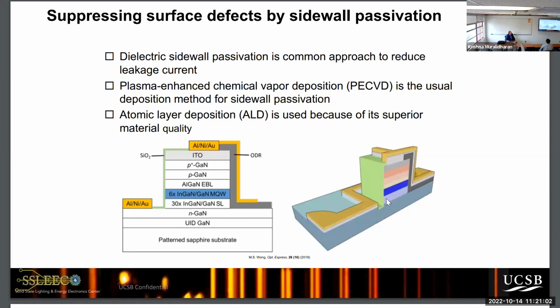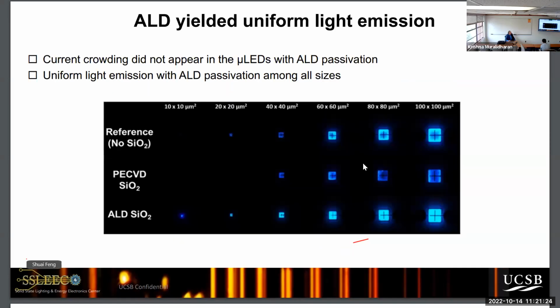Yeah, there is a thickness dependence on the quantum. So these are, like I said, 10 micron by 10 micron. We've actually made them 1 by 1, and the height is half a micron. But the thickness dependency is in the quantum well. It's 30 angstroms thick. I see. That's what you get from the layered process. Very good. Okay. Very clear. Thank you. So very small now in the lateral dimensions. But 10 by 10 microns is honestly good enough for most display applications.